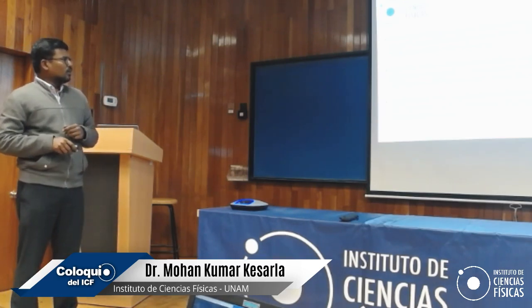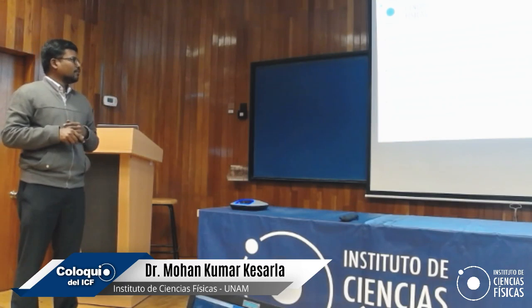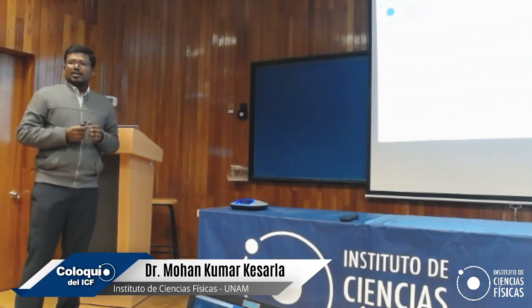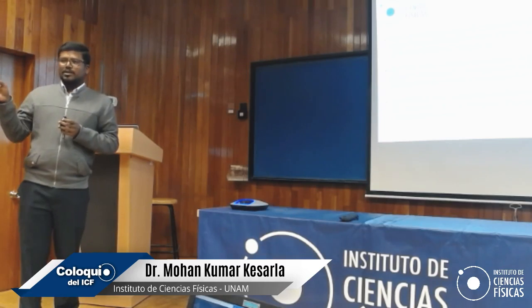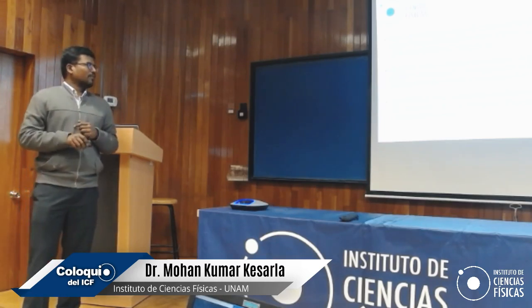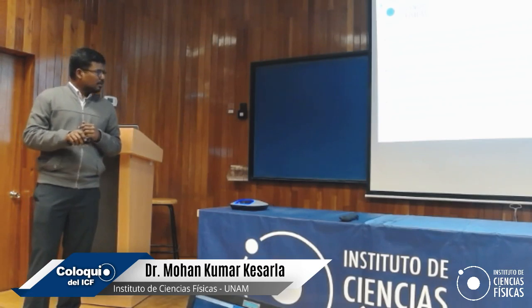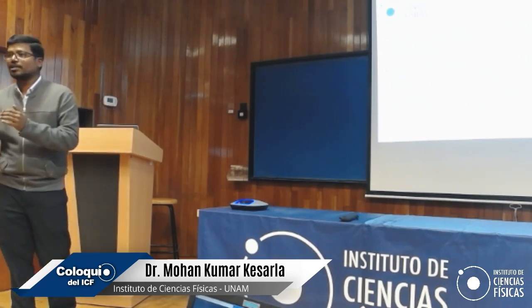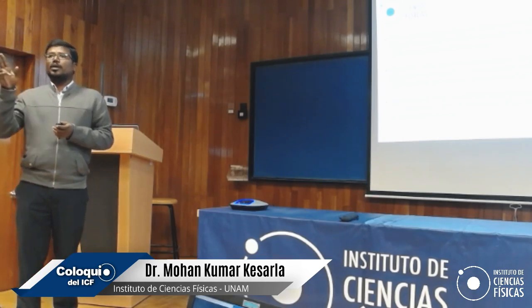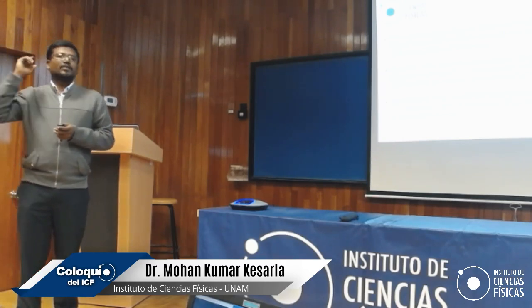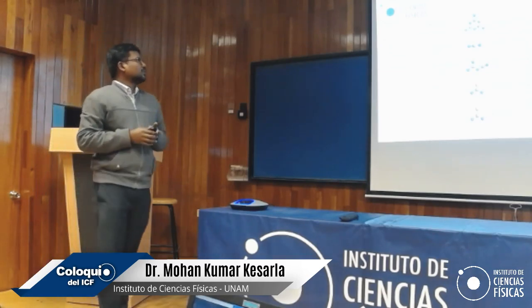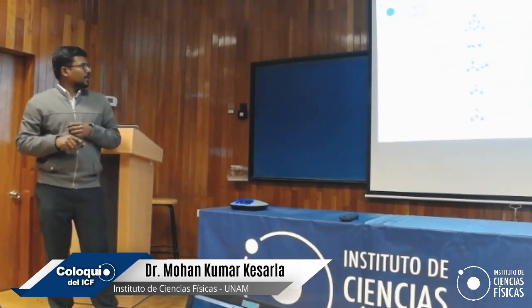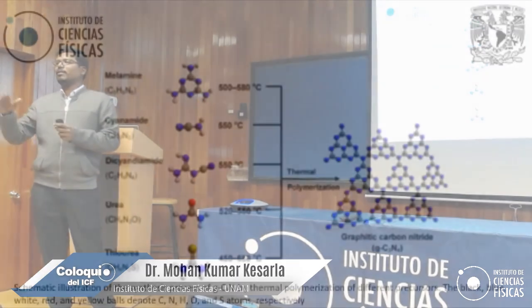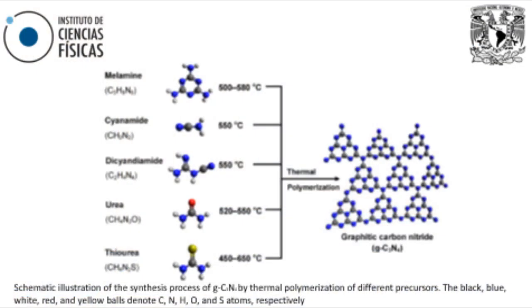So what is the good thing with g-C3N4? It is earth abundant, and it is very simple to fabricate this g-C3N4, and you can use very cheap chemicals like melamine and dicyandiamide, which are rich in carbon and nitrogen, in order to prepare this two-dimensional polymeric graphitic carbon nitride, which has a band gap in the visible region. So you just take any one of these precursors, either melamine, cyanamide, dicyandiamide, urea, or thiourea, and you just heat it to more than 500 degrees. And why 500 degrees? This is based on the TGA-DTA experiments, and you can get the polymeric graphitic carbon nitride.